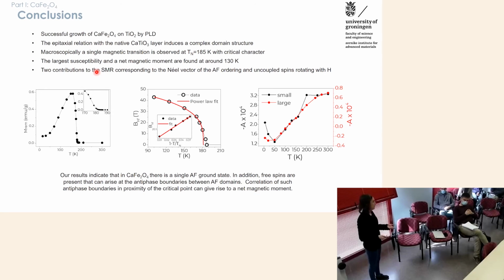And we also observe that there are two components in this ordering, an antiferromagnetic component and a component of these uncoupled spins. So what we think is that these uncoupled spins at the antiphase boundaries are usually non-interacting because the antiphase boundaries are quite far away from each other. And what happens close to the Néel temperature, so close to the critical temperature, is that there are longer range interactions which allow the spins to interact together and generate some net magnetization in the system.